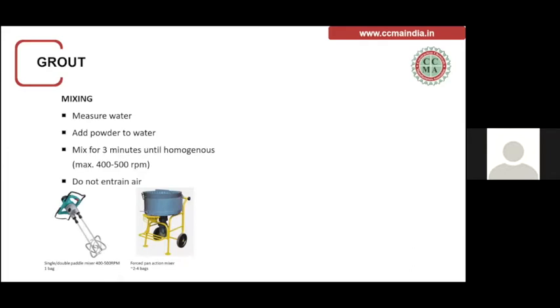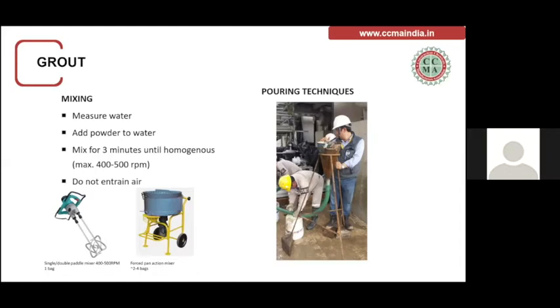Another important aspect: the mixing should not be done at a very high RPM, because there are chances that air gets entrapped, or if the spindle is moved in an upward and downward direction, the air will get entrapped in the grout, and air bubbles are not good for the grout consistency. For pouring, because these grouts have to flow, we should create a desired pressure head so that the grout flows with gravity and fills all the joints.